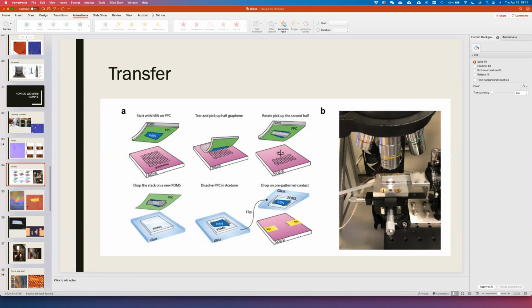Okay, yeah. I'd like to know if superconducting graphene follows Mattis-Bardeen behavior, or other, how the impedance compares to other superconductors. Oh, I see. Yeah, that would be interesting. But because the sample is usually small and there's some angle, there will be strain, so your angle can be different at different areas. So unless you can shrink your bin size to very small, a lot of the time you will just get a lot of blurring effect from the angle inhomogeneity. So that would be a very challenging experiment, I think.